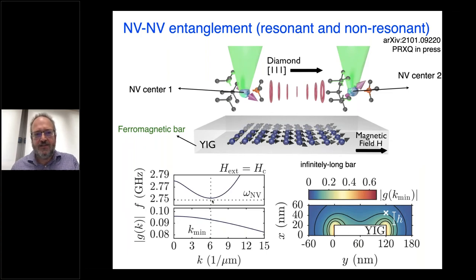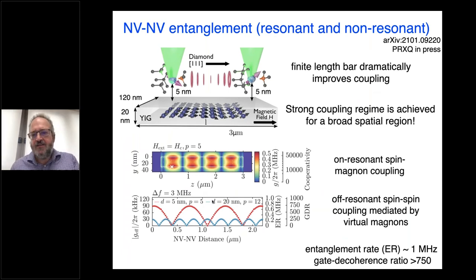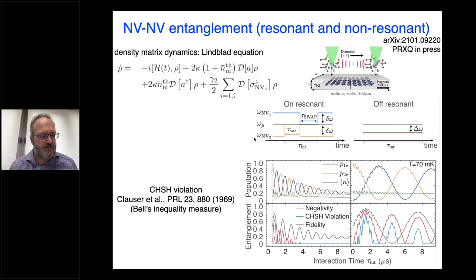If we're just trying to do entanglement, it turns out that this geometry has some advantages. In particular, we can do non-resonant entanglement and take advantage of a minimum in the dispersion of magnons, which will give you a large density of states coupling the two NVs together. So we've then calculated this coupling, and we find that the entanglement rate for these NVs, for a somewhat aggressive geometry here, the main aggressive aspect is this 5 nanometers below the diamond surface of the NV. This kind of bar of YIG is perfectly reasonable, 20 nanometers by 120 by 3 microns. We find entanglement rates on the order of a megahertz and gate to decoherence ratios of order 750. So this means it should be a very efficient way to get good NV-NV entanglement.